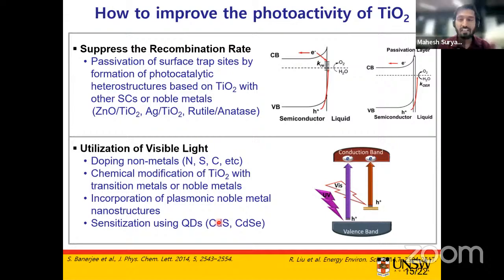Next, its energy levels are appropriate to initiate the water splitting reaction. However, the efficiency of PEC water splitting using TiO2 is still relatively low compared to other materials that have been reported so far. There are several reasons for this, such as the different recombination processes that occur in TiO2. So how can we improve the efficiency of TiO2? We can improve it by passivating the surface states through the formation of catalytic heterostructures based on TiO2 with other semiconductors or noble metals.